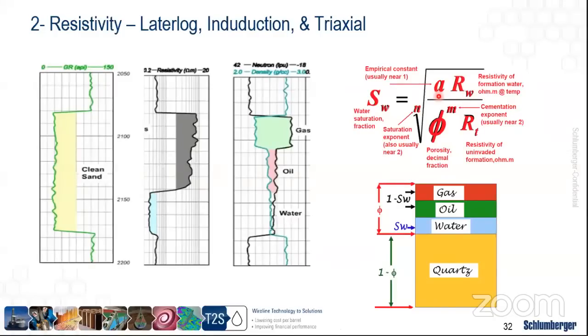We have A as 1, we have porosity using the cross plots between the neutron porosity and the bulk density. We have M assumed as 2, N is also assumed as 2, and RT coming directly from the tool, AT90, RLA5, or RV. Then we can calculate SW at each and every point of the reservoir, and then we subtract SW from 1 in order to compute how much hydrocarbon saturation we have in place.